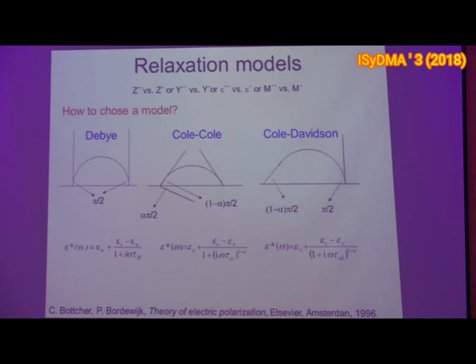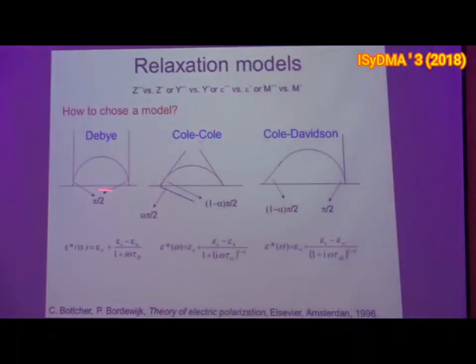So then we have different models. We have the different data. That is, we make the measurements with time, with temperature, and with frequency, and we make these diagrams, the Nyquist diagrams. In this case, we use, for example, the imaginary part of permittivity as a function of the real part, to see what is the shape of this graphic that you have here.